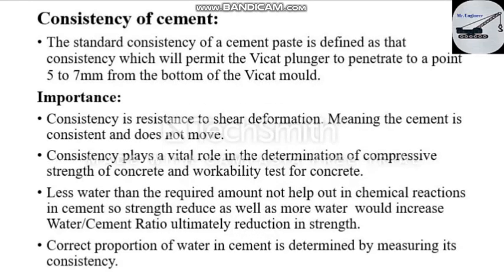First of all we should know what is standard consistency and why it is important. The standard consistency of a cement paste is defined as that consistency which will permit the Vicat plunger to penetrate to a point 5 to 7 mm from the bottom of the Vicat mold.